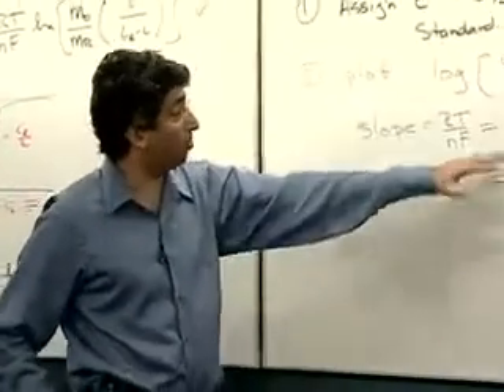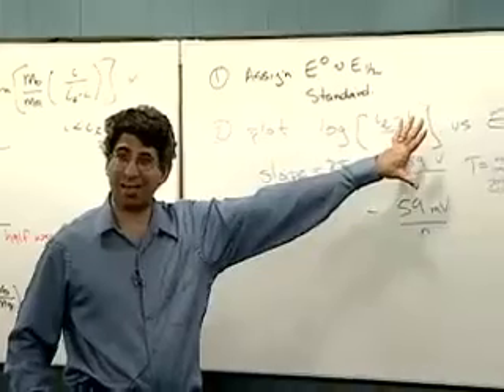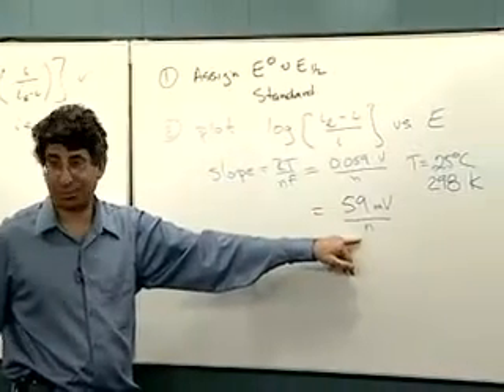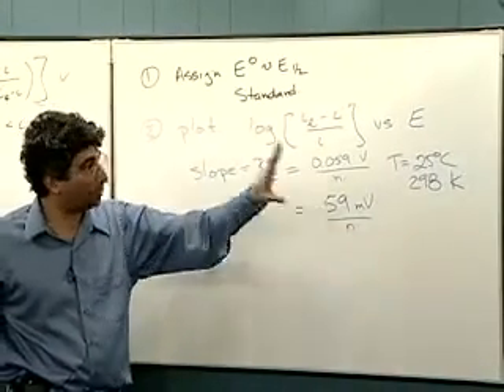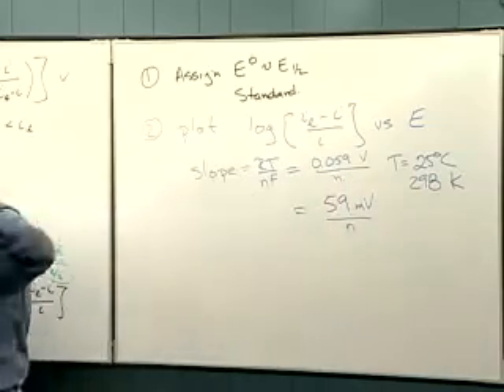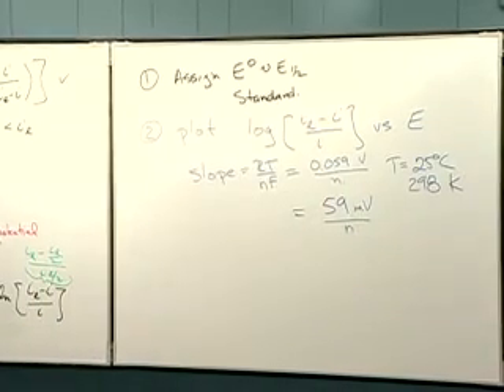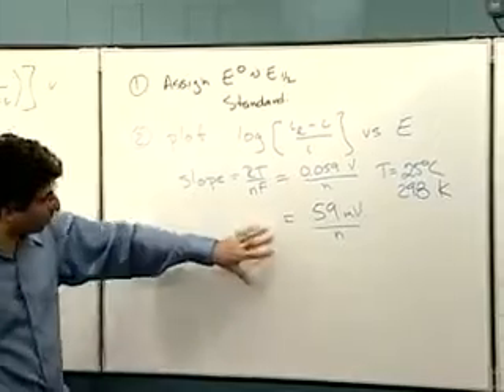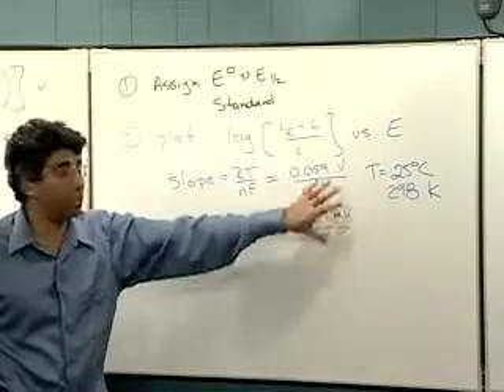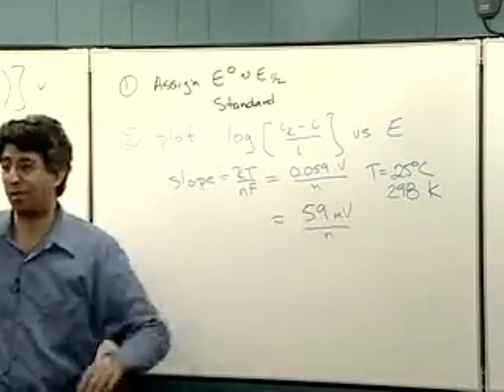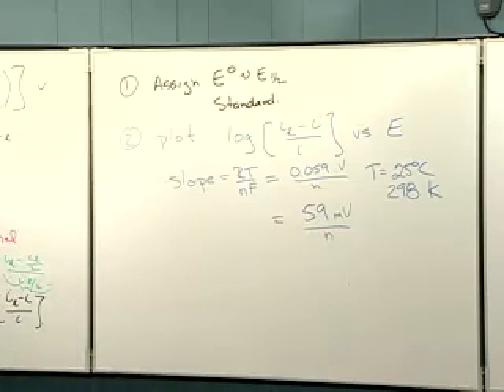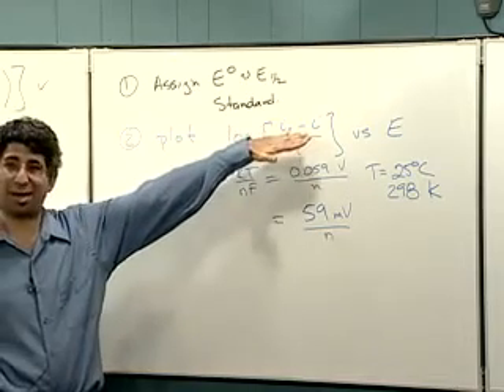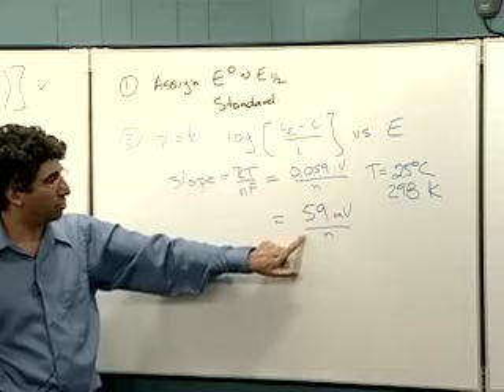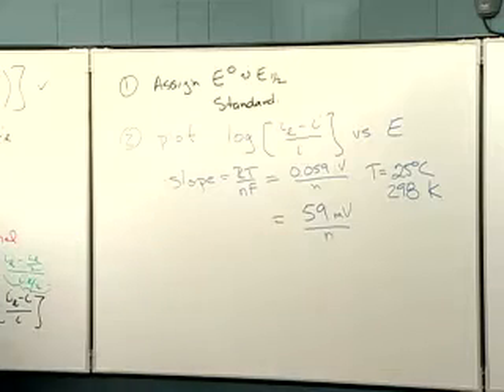First thing about this is, of course, if I don't, for some reason, know what n is, I can back n out of this, assuming that I'm certain that I'm diffusion limited or mass transport limited in general. If I do know what n is, then I can use this as a test to see if, in fact, I meet the condition of being mass transport limited. And typically, I would know what n is. So in other words, if I make that plot and it's not a straight line with that slope, I'm not mass transport limited.